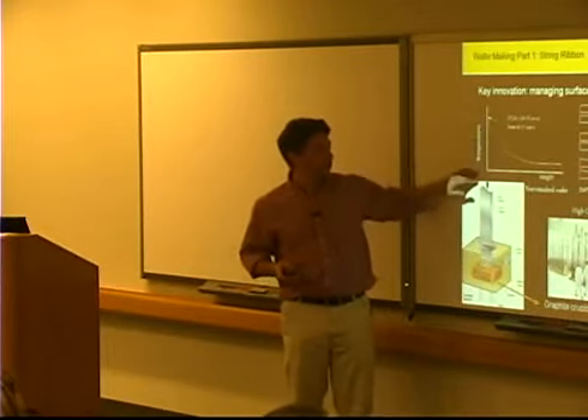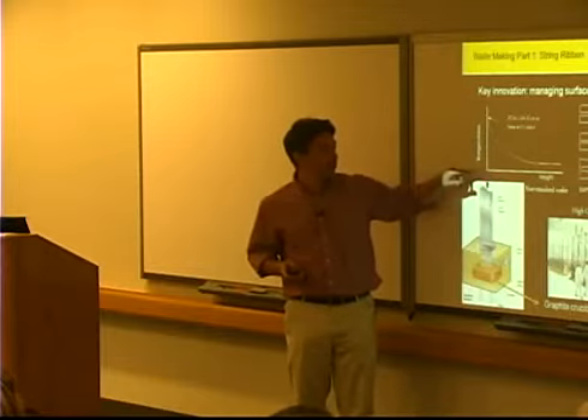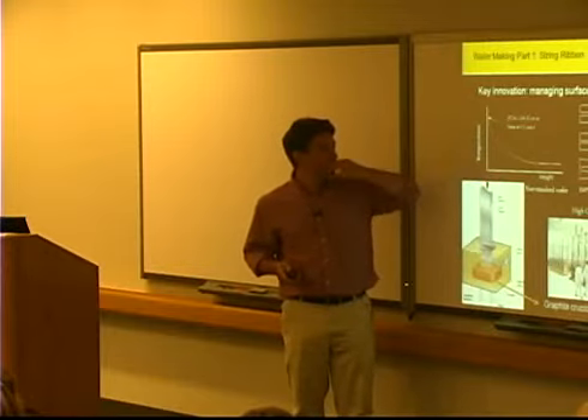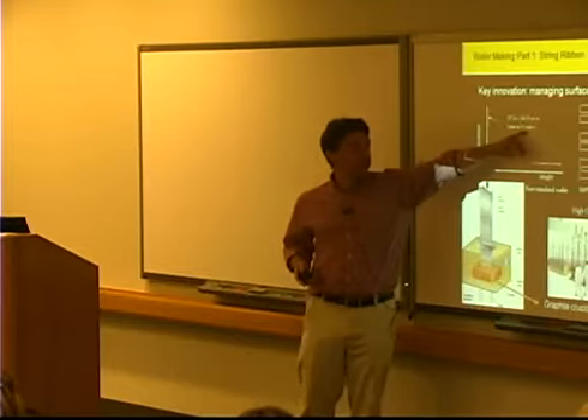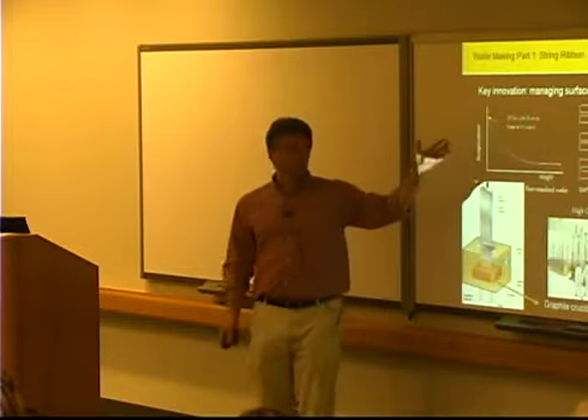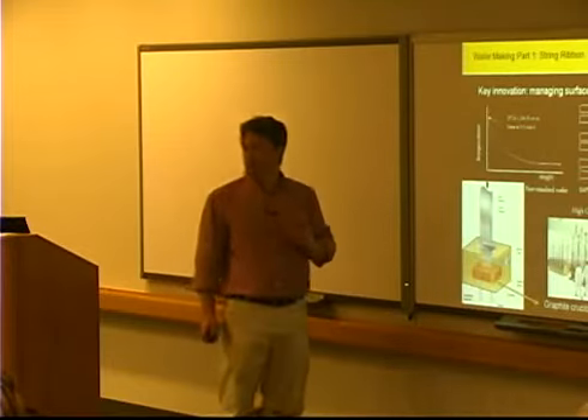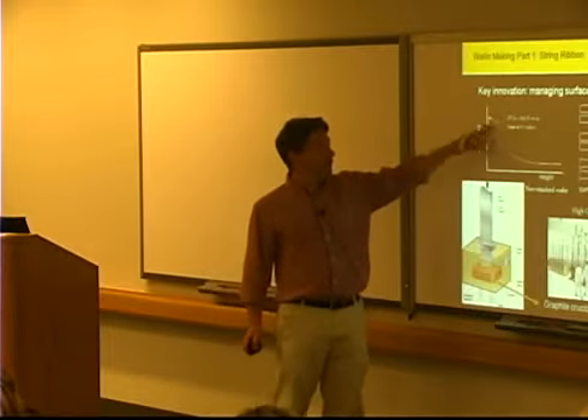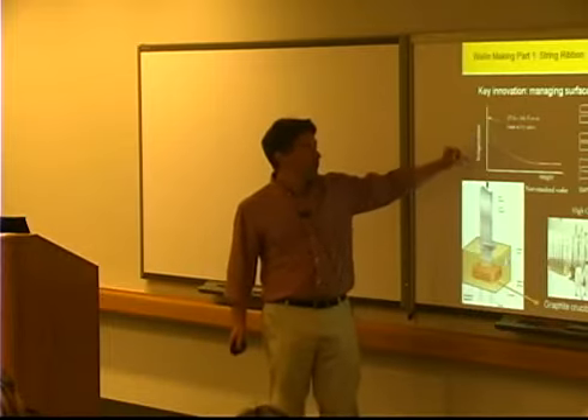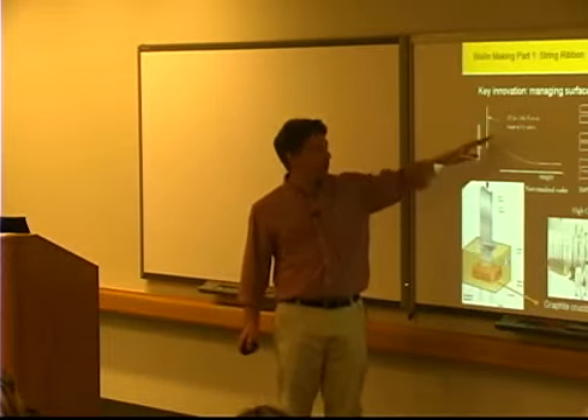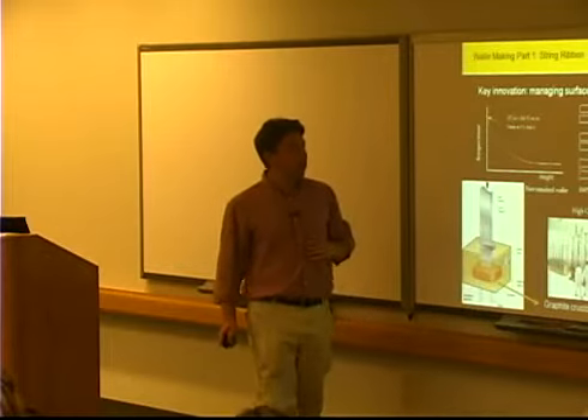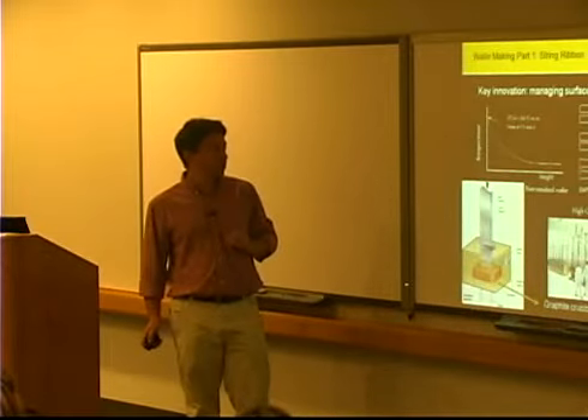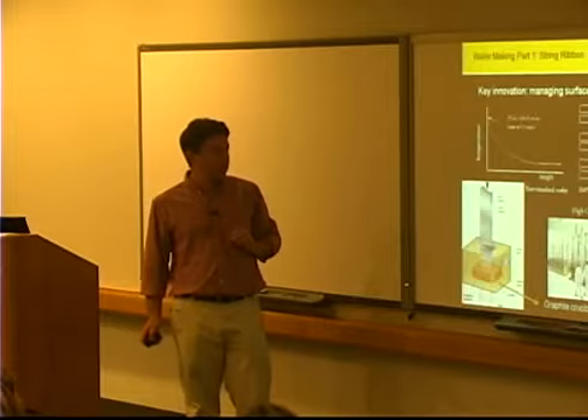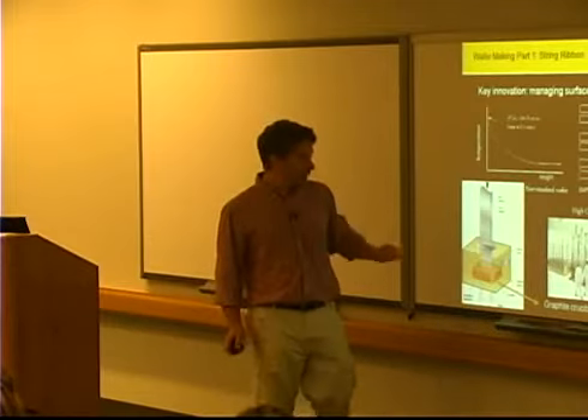Here's a temperature versus height graph. If you want to freeze at even 0.3 millimeters per second, which is, again, a factor of 3 lower than my kind of target value, you need a change of temperature with height of more than 500 kelvins per centimeter. And that's pretty extreme. It leads to relatively high stress.